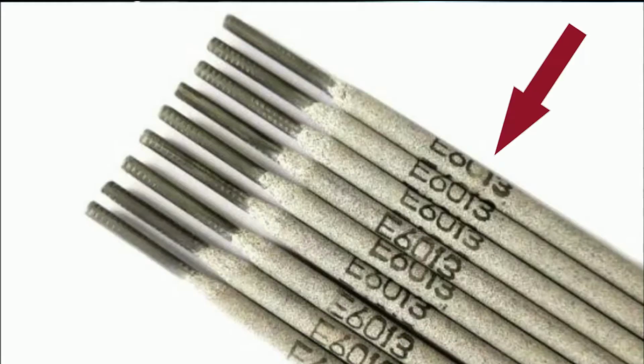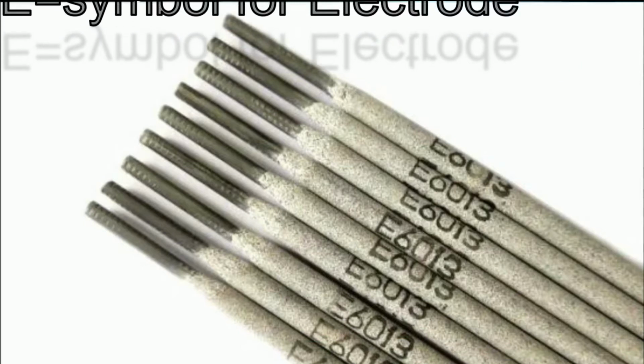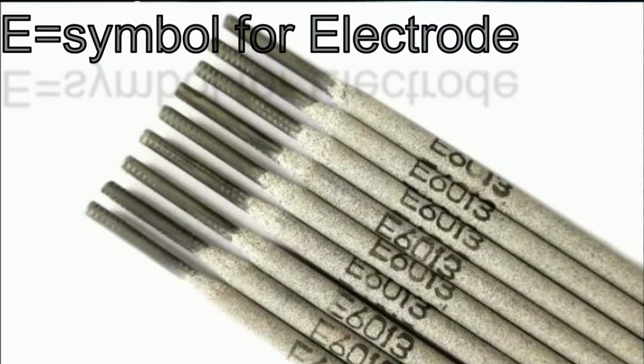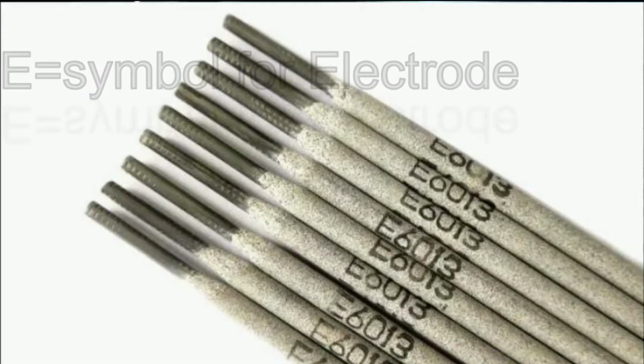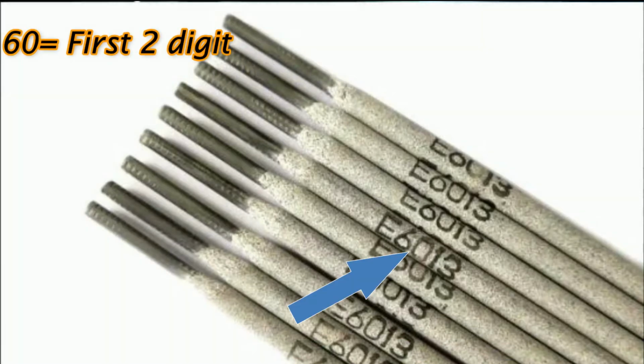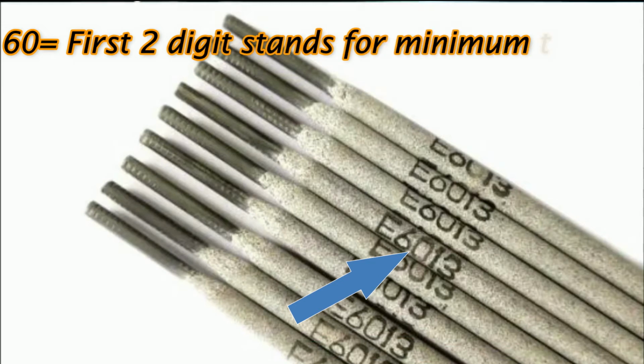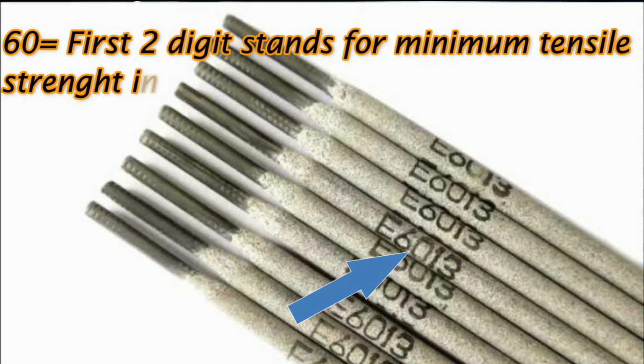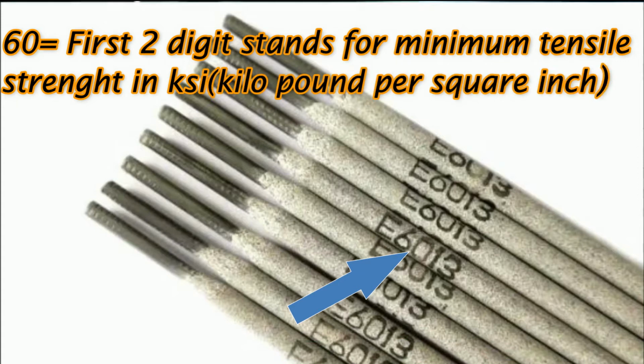In this electrode, you can find E6013, which is a mild steel electrode, as I have said earlier. Here you can see a letter E, which is nothing but just a symbol of electrode. Now, the first two digits, which is 60, indicates the minimum tensile strength of the electrode, which is 60 kilopound per square inch. So, let me elaborate more.